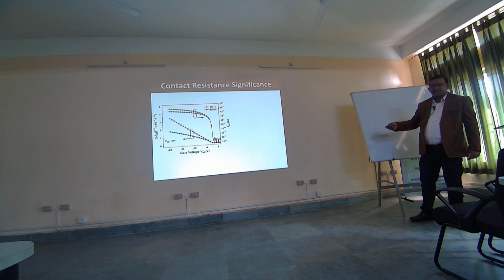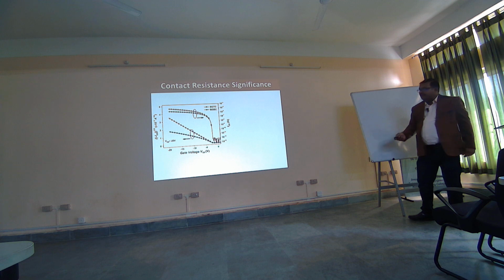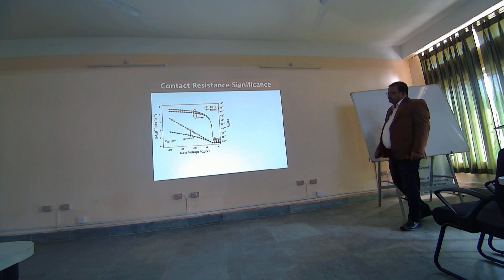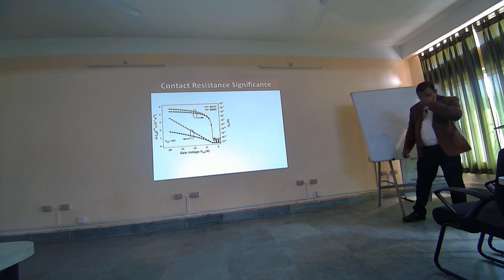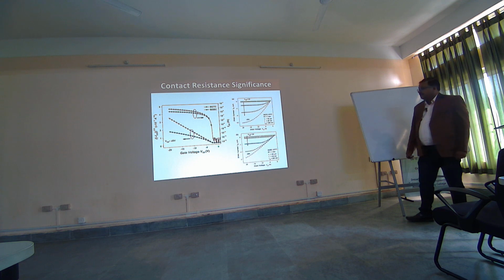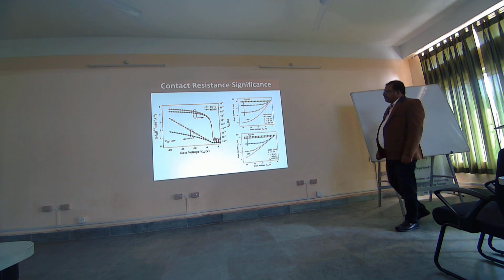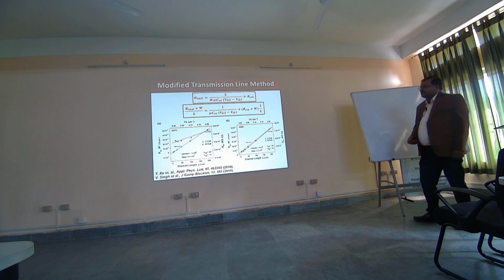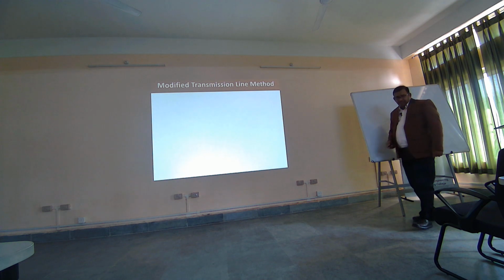In the on state, drive currents are higher in magnitude compared to bottom contact, and that is how our interest in contact resistance started, and we further tried to investigate this. So these are the output characteristics of BGTC and BGBC MOSFETs. Both output and transfer characteristics showed that BGTC has a better, or reduced, contact resistance.